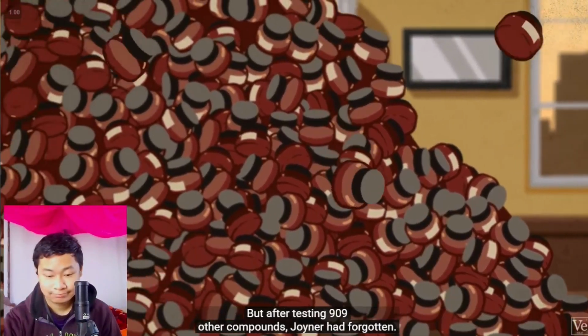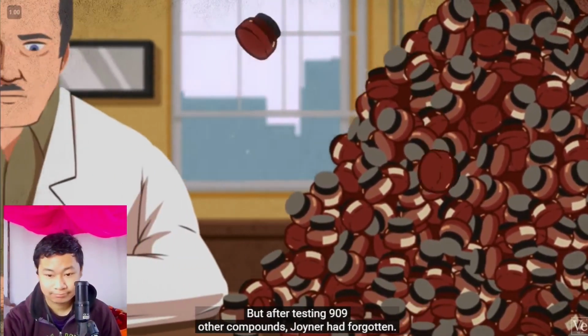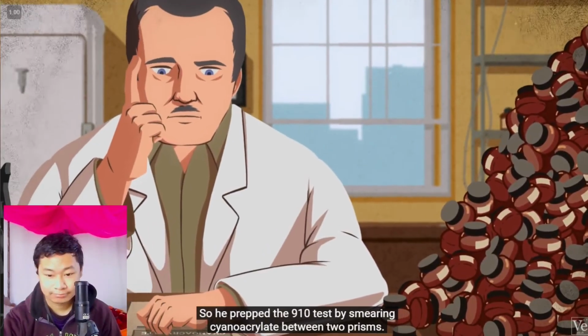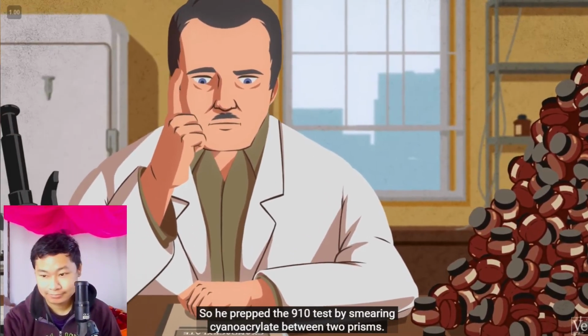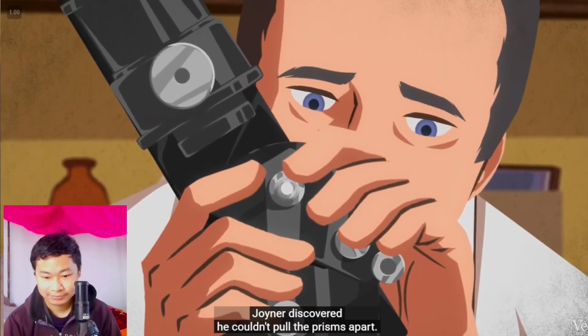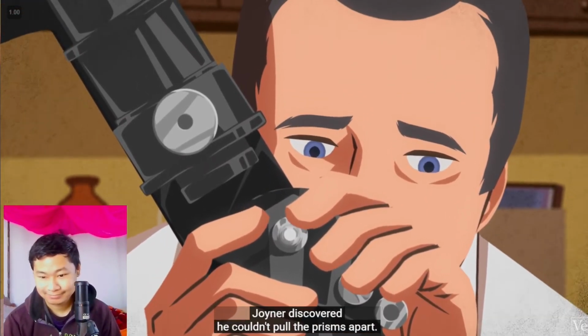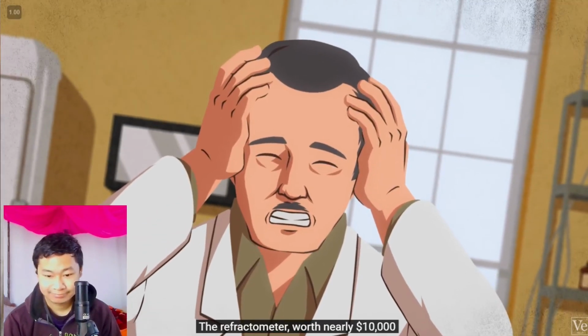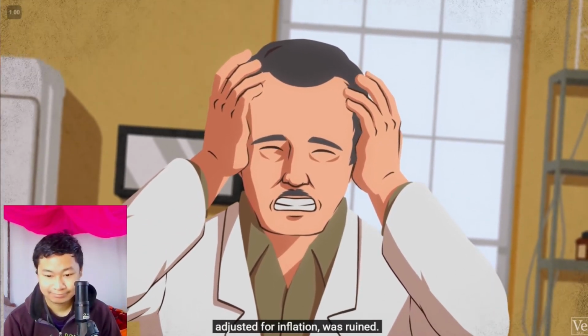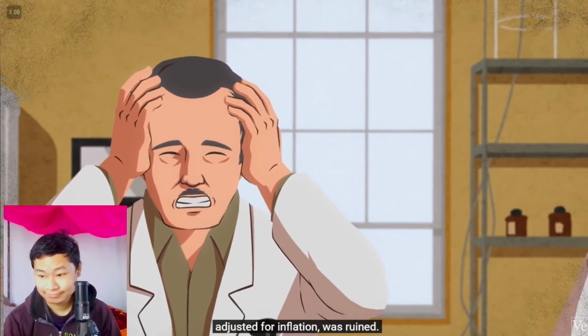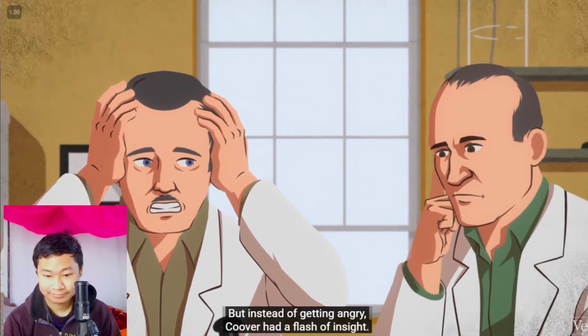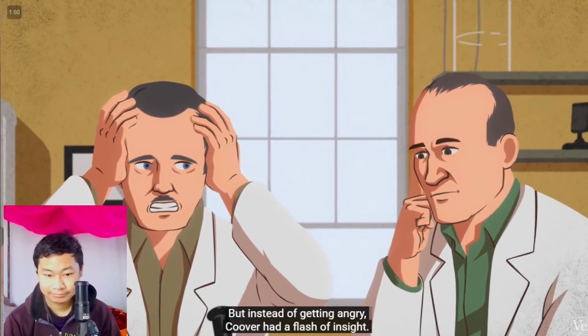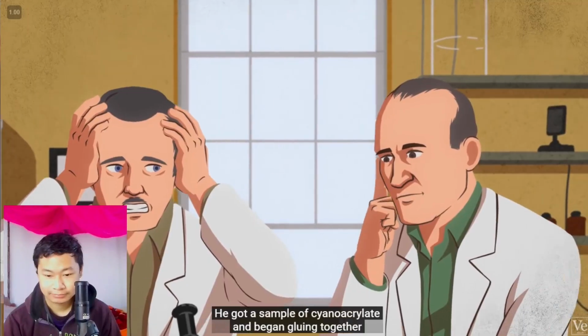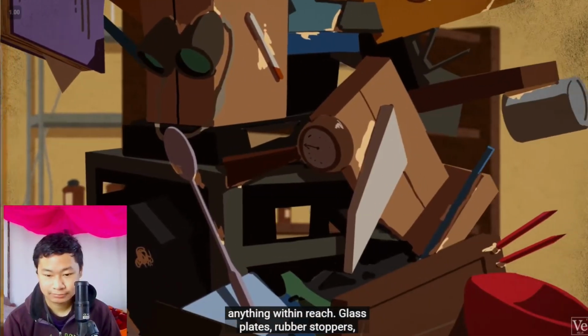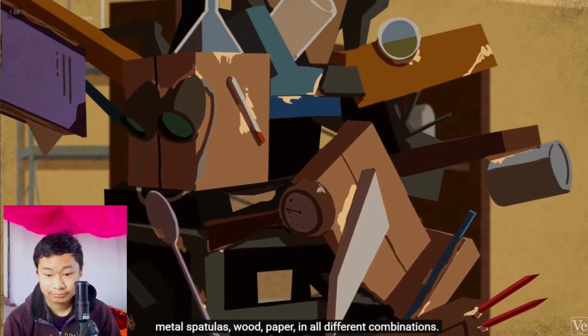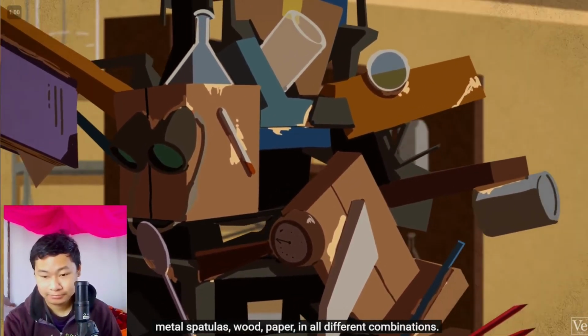But after testing 909 other compounds, Joyner had forgotten. So he prepped the 910th test by smearing cyanoacrylate between two prisms. After taking the measurement, Joyner discovered he couldn't pull the prisms apart. He panicked. The refractometer, worth nearly $10,000 adjusted for inflation, was ruined. But instead of getting angry, Coover had a flash of insight. He got a sample of cyanoacrylate and began gluing together anything within reach: glass plates, rubber stoppers, metal spatulas, wood, paper, in all different combinations.